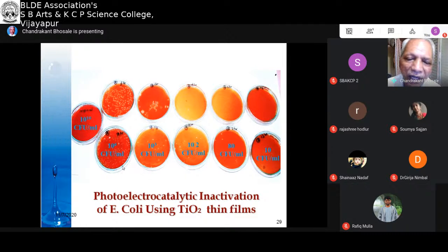After half an hour, the number of bacteria remaining is 10 raised to 6 CFU, colony forming units per ml. Then again after half an hour, the number of bacteria becomes 10 raised to 3. Then again after half an hour, 10 raised to 2. Then after half an hour, just 80. And after half an hour, just 10 CFU per ml. So what we notice from these figures is that bacteria can be killed in this reactor, and you can have purified water using this reactor.